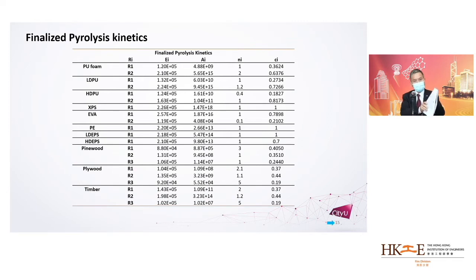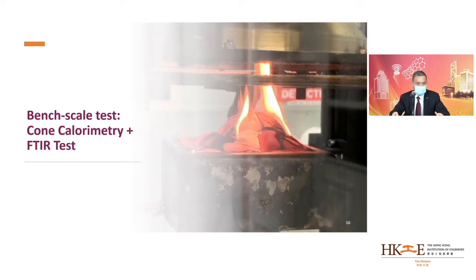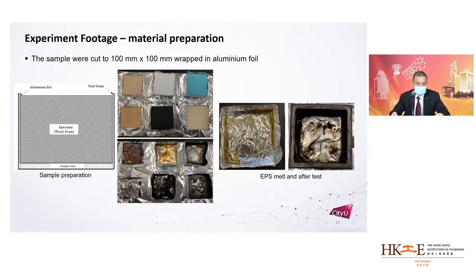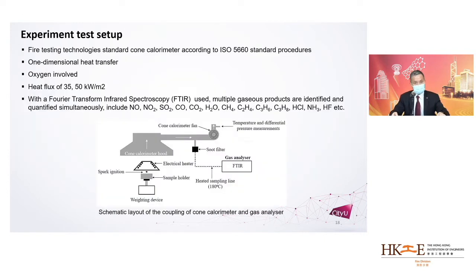And finally, I would like to present to you a couple of validations by using fire tests. Firstly, by bench-type tests at a bench scale. The cone calorimeter has been a very useful bench-type equipment to explore the burning characteristics of composite materials. Here are some of the samples before and after burning in the cone calorimeter. And because of the timing, I would like to go very quickly. A cone calorimeter consists of a radiation heater where the sample is placed on the sample holder, and the dimension is standardized so that when we excite the material by the radiation heater, the material can be ignited by a spark, and there we can measure the heat release rate as well as the gas emissions from the burning material.